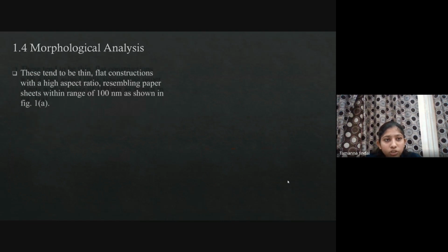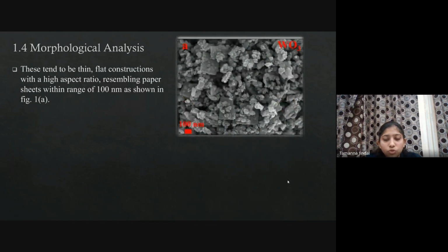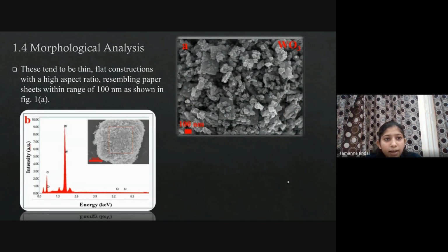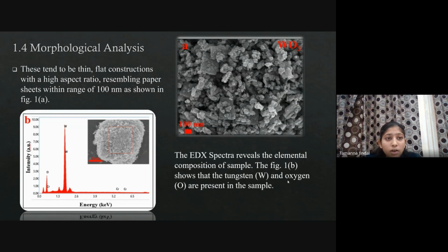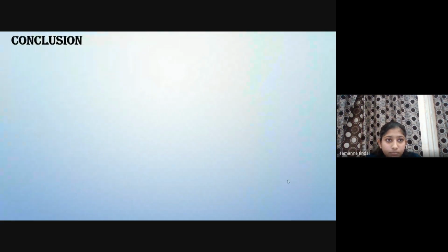Now the morphological analysis, which is shown by this figure: there is a thin flat structure with a high aspect ratio resembling paper sheets within the range of 100 nanometer as shown in the figure. FESEM also includes the EDS spectra, which reveals the elemental composition of the sample. And here, as shown in the figure, the highest peaks of tungsten and oxygen are present in the sample.